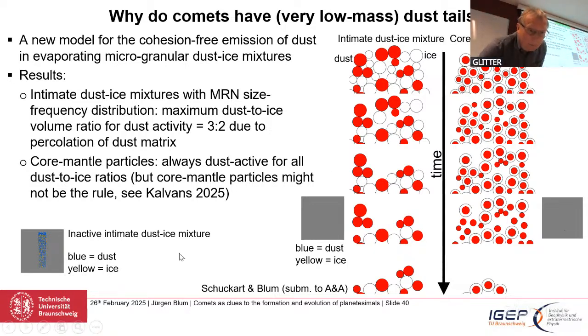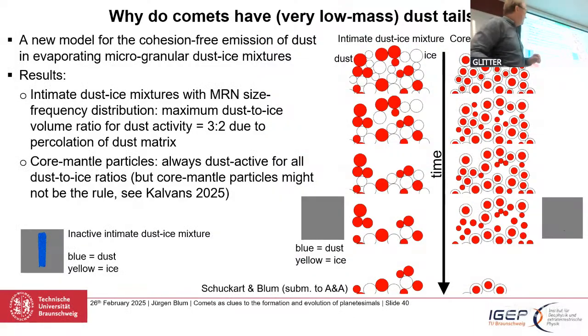Why is that? Well, we varied the dust to ice ratio. Again, the blue is the dust, the yellow is the ice. And here we are. Here is an inactive part of a comet. So there's too much dust for the ice to overcome the cohesion at some point. There are always bonds between dust particles left over. So that's the idea here. And it turns out this cannot be the case for comets. So comets cannot be core-mantle particles because they would expel all their dust into the tail, which is not what we observe. It can be like that, but a small amount of dust is only expelled if most of the volume of the comet has a dust to ice volume ratio of 3:2 or a dust to ice mass ratio of 3:1 roughly.